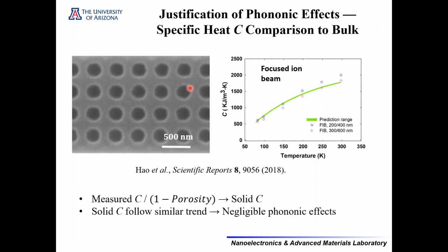So my next question is, does the nature of the nanoparticles affect the phononic effect, like we have nanoparticles amorphous and crystalline in nature? So should it be crystalline in nature for the study of phononic effect? Phononic effects really require very smooth pore edges, because if you have rough pore edges, phonons will be diffusively scattered, and that diffusive phonon scattering will randomize the phonon phase, and you will never have coherent phonon transport in that case.